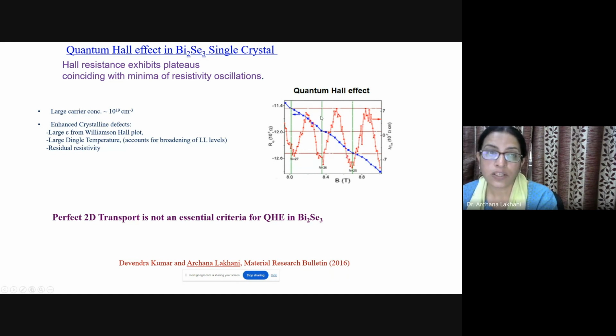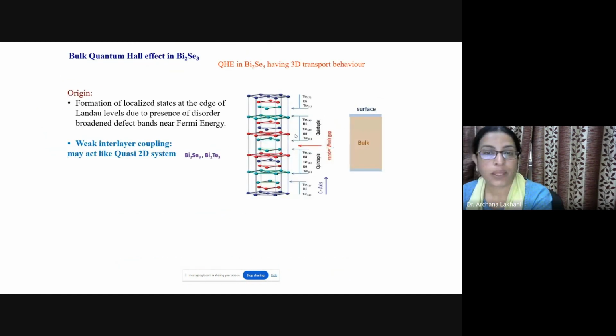And this had a large carrier concentration and a few optimized enhanced crystalline effects. And this was because the quantum Hall effect in this particular crystal could be observed because of either weak interlayer coupling in the system or due to the formation of Landau localized states at the edges of the Landau level due to the presence of a particular disorder in this system.